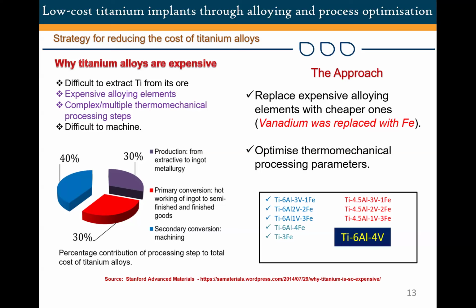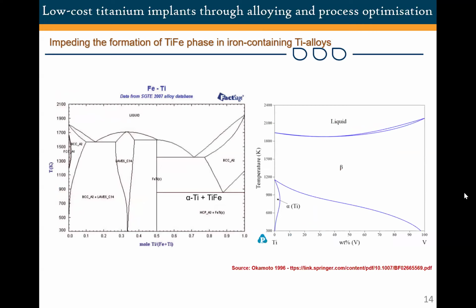So if we look at Ti64, many people or previous researchers have tried to substitute 4 weight percent of vanadium with 4 weight percent of iron. The major problem is that you would form this phase. Now I'm going a bit into physical metallurgy, and this is the domain of Professor Cornish, actually, phase diagram. So if you add iron to titanium, the equilibrium phases you would have are what we call alpha titanium, which is the stable phase of pure titanium with a hexagonal close packed crystal structure, and of course, you also have the TiFe intermetallic compound.